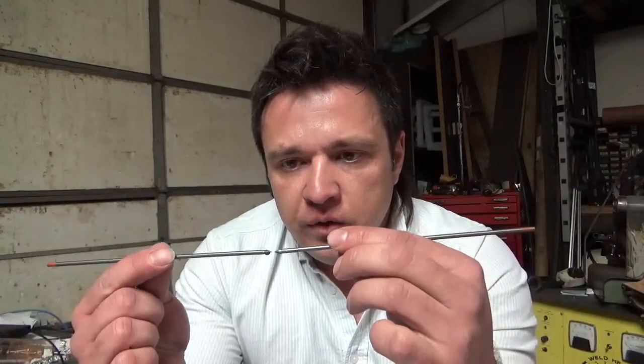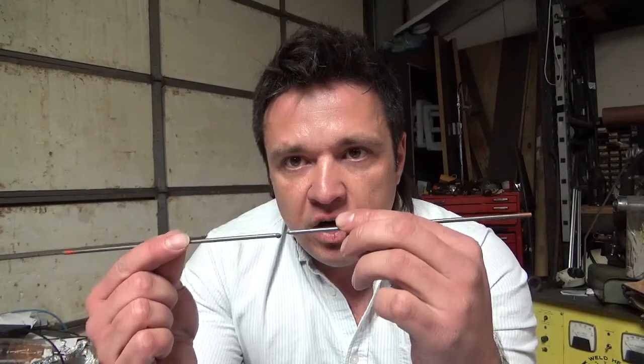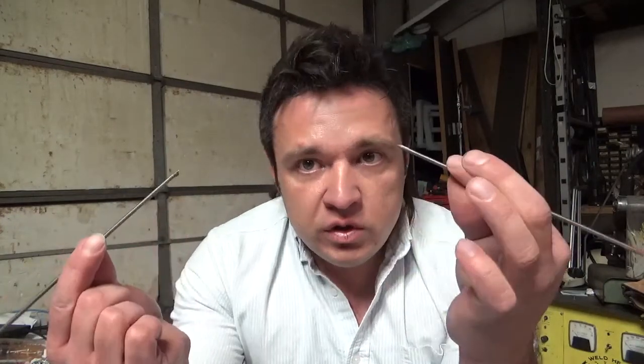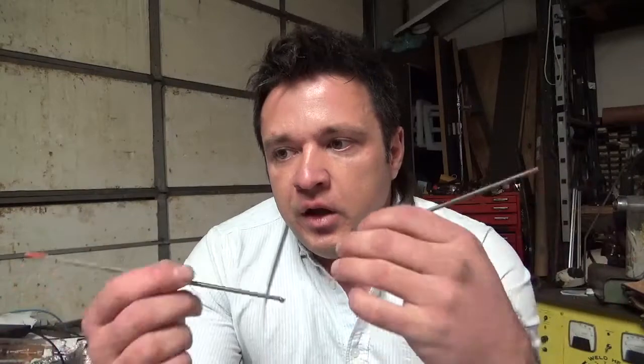Now, the method I'm most familiar with and would like to use is the arc plasma method, similar to apparatus used by Kretschmer. So in this method, as mentioned earlier, one would take two graphite electrodes and then light an arc between the two of them, similar to what you might do with welding. The resulting vapor will then grow very high quality nanotubes with narrow diameters and very few structural defects.